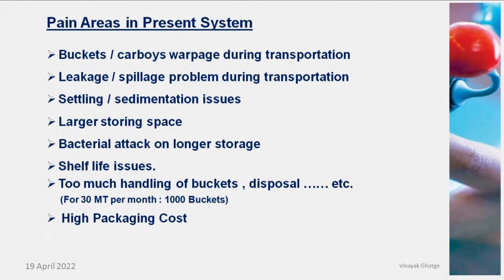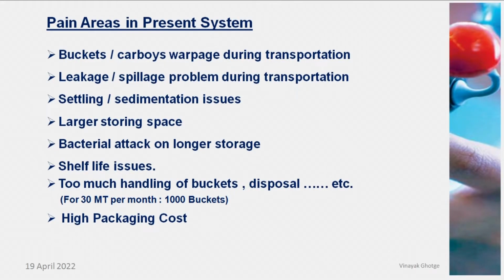What are the pain areas in the present system? The buckets and carboys warpage during transportation, leakage, spillage problems during transportation, settling and sedimentation issues, a perennial problem, and large storing space because the buckets need larger space for storage. Bacterial attack on longer storage, especially in high temperature ambient conditions, the bacterial attack is quite fast. And shelf life issues. Normally most of the water-based coatings have about 6 months shelf life, but in case of very high ambient temperatures, the bacterial attack can be even faster.